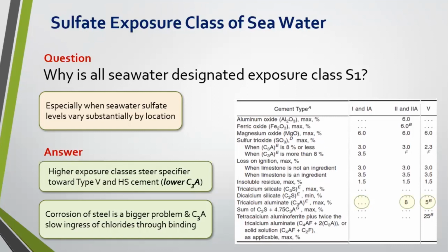The reason that we're looking at S1 for seawater is because we have to look at the entire picture here. When you're talking about seawater, it's not just sulfate resistance that we're talking about. One of the primary concerns when you're dealing with seawater is ingress of chlorides. When you get chlorides to the reinforcing steel, you're dealing with all sorts of problems. So C3A at the early part of this presentation was wearing a black hat. Right now, it's actually doing some good because the C3A is going to bind some of those chlorides and slow the ingress of those chlorides to our reinforcing steel.